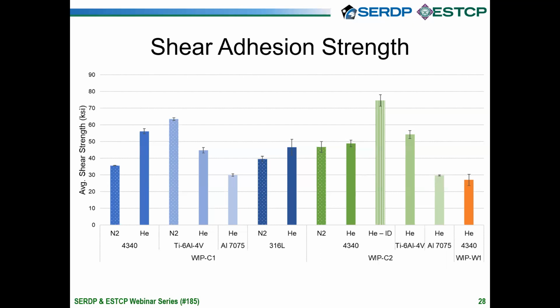So basically the passing criteria for a thermal spray coating is at least 10 KSI tensile strength. What we evaluated was the shear strength, which is typically about half of the tensile strength for a material. And we found that all of our shear strengths were at least 20 KSI, which is twice the pass-fail criteria for a thermal spray coating.